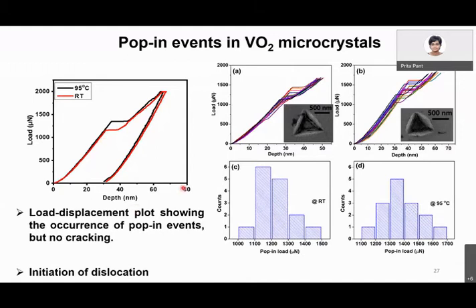Yeah, that's a very good question. In shape memory alloys, one of the problems during multiple cycling, due to the memory effect or plasticity effect, is that you start seeing a compromise in the recoverable stress. Whereas VO2, being a ceramic material, has relatively negligible plasticity. The curve I'm showing here is at 2 millinewton, and we have around 30 nanometers of permanent deformation. The actuation measurement I was telling you about uses a much smaller load. So the answer to your question is, definitely there is plastic deformation, but it is negligible.